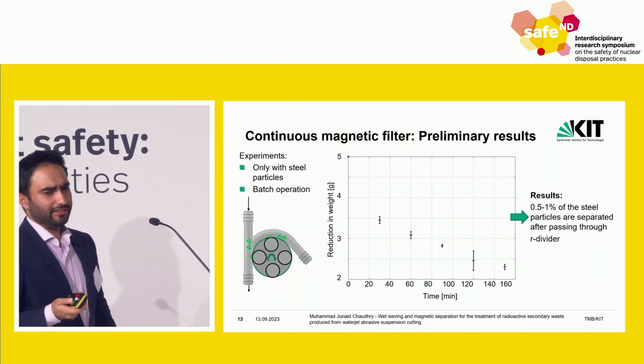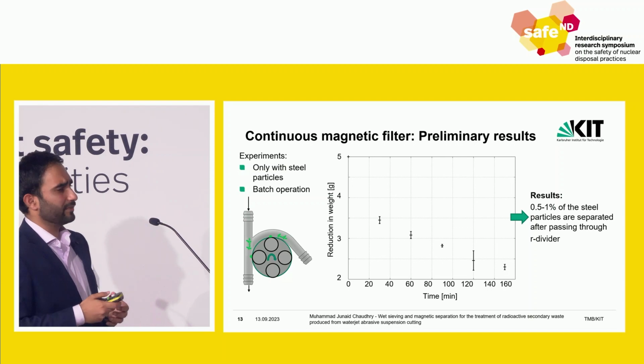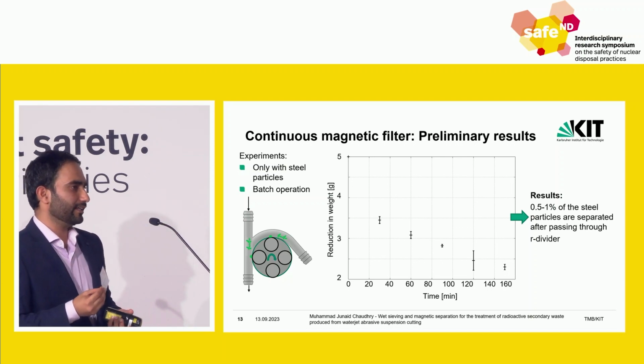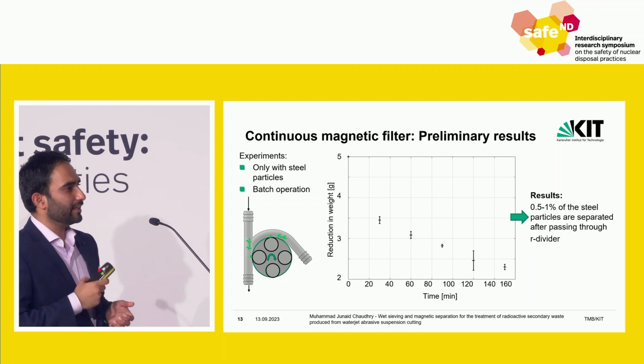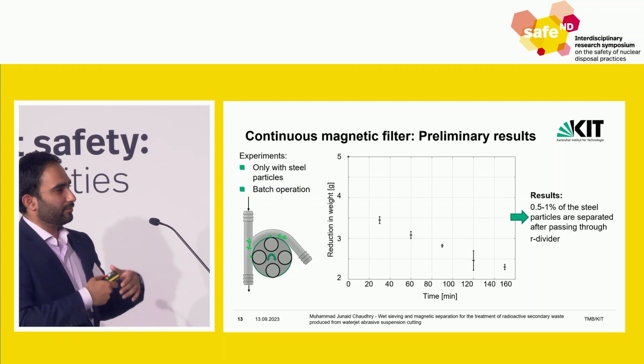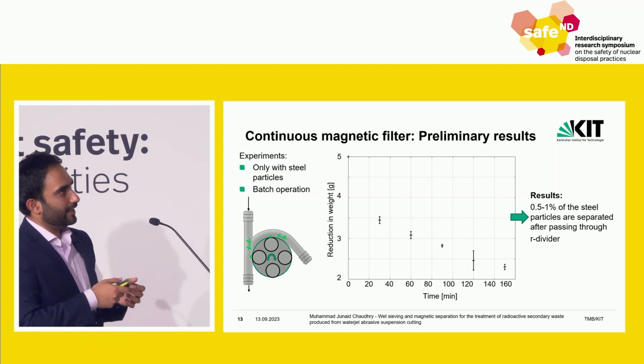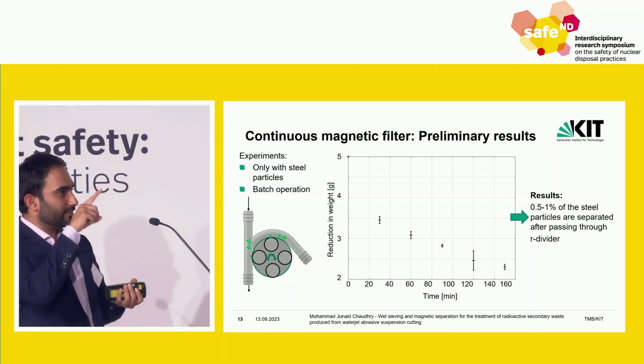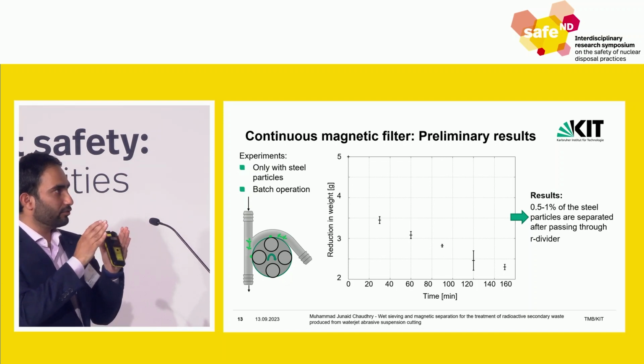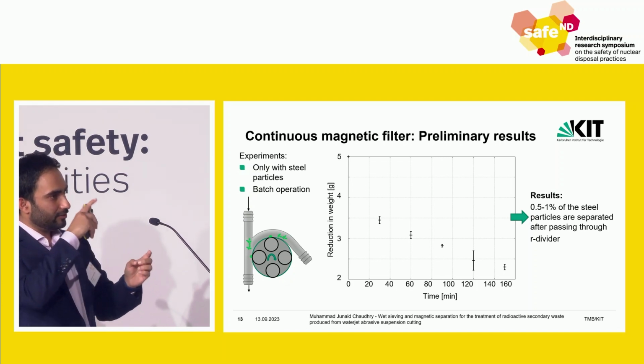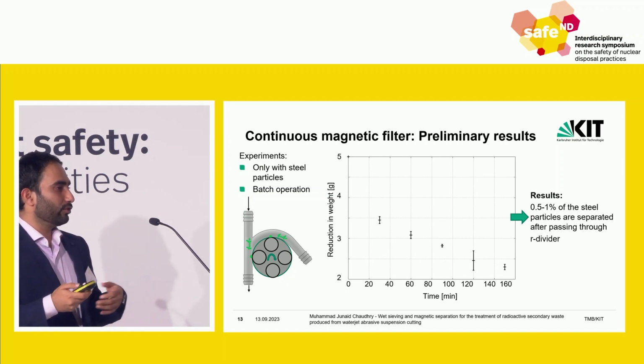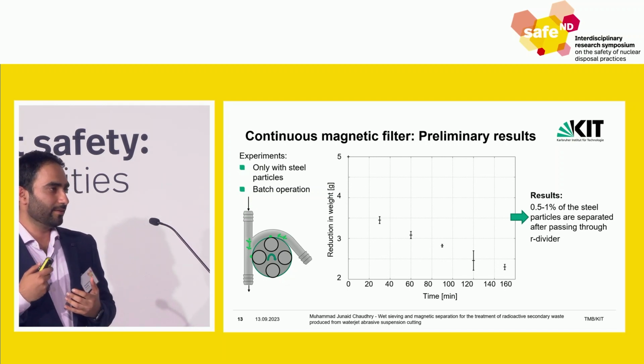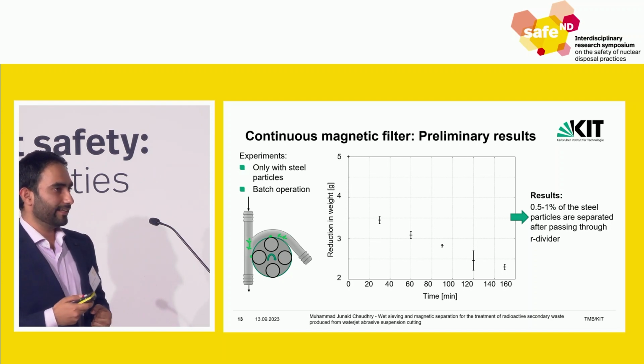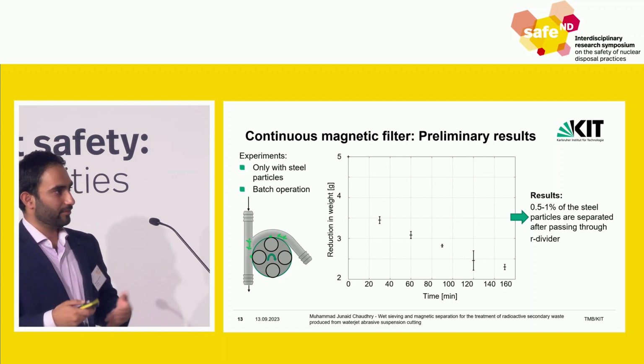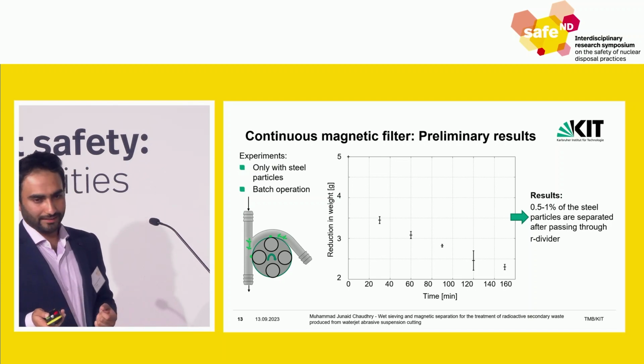So the preliminary results from the first experiment we performed: we took only steel particles, 5 grams of steel particles, and ran it for 20 minutes as a batch operation. From the theoretical extrapolation, we saw that for every cycle, it separates 0.5 to 1% of the steel particles in just one rotation. As I told you, this is just the first step, and we are still hopeful that we will perform much better with the results.